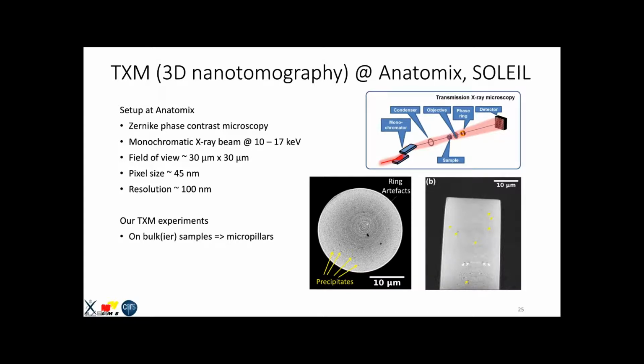So this is in the top down direction. And if you see the side view at a slice, you can see that these ring artifacts manifest as ghost precipitates, which are really not precipitates, they are just artifacts over here that are mirror imaged along this line. Okay, so we map them via TXM. Great. How do we perform solid state thermal cycling on micropillars?